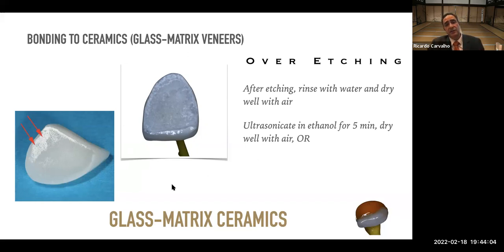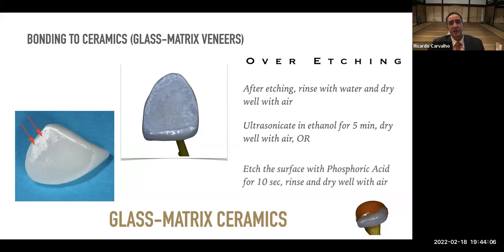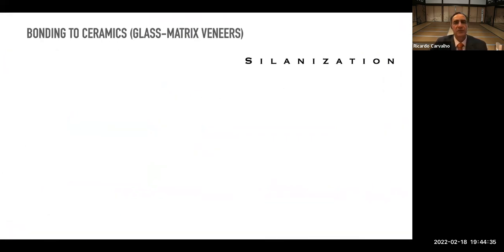Or better yet, since you are chairside, you are seeing your patients, the easiest way to remove those debris is by just simply etching the surface now with phosphoric acid, the same acid we use for bonding to the enamel or dentin. We just quickly apply on the surface for 10 seconds. We rinse and dry well. Phosphoric acid will then dissolve these salts, remove the debris, the residue, allowing then the surface ready for silanization.